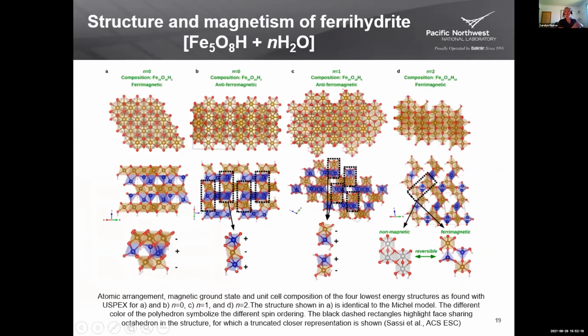So goethite, we're getting progressively less and less magnetic, and now we're moving into the realm of ferrihydrite. There's been much debate on the structure of ferrihydrite and its magnetic properties. And this was again a study by Michel Sassi, where he used DFT calculations to predict thermodynamically stable structures for ferrihydrite as a function of composition and water content, and relating that to the magnetic properties.